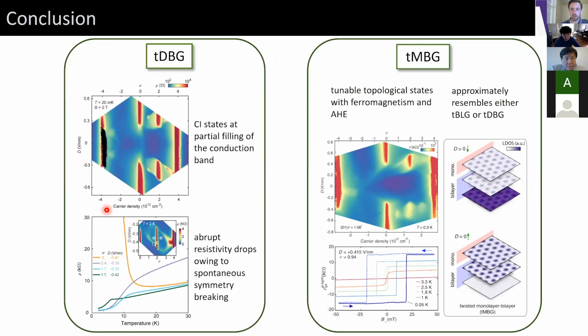All right, so in conclusion, I've primarily shown you transport in two different twisted graphene multilayer systems. In twisted double bilayer graphene, we have electric field tunable correlated insulating states, and then signatures of spontaneous symmetry breaking in the neighboring metallic states. And in twisted monolayer-bilayer graphene, we have a system that resembles both twisted bilayer graphene and twisted double bilayer graphene, with some important differences, including the ability to realize a robust anomalous Hall phase in ferromagnetism at quarter filling of the band.